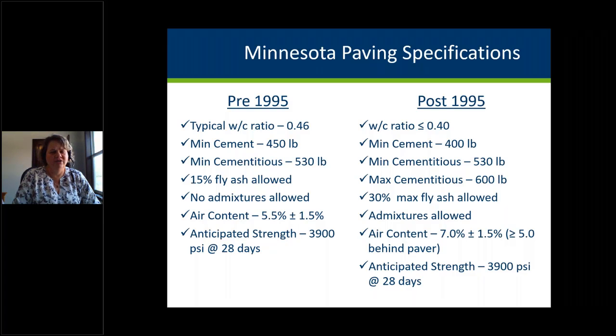And so what Jason just talked about quite a bit was the use of SCMs. Our pavements prior to our change really limited the amount of SCMs in there. Plus we didn't mitigate at all. We didn't use any admixtures other than air entraining agent prior to 1995. And as I said, we anticipated strength. Post 1995, we were up to allowing 30% max fly ash, requiring some for mitigation of ASR. Our current specs are 33% fly ash.